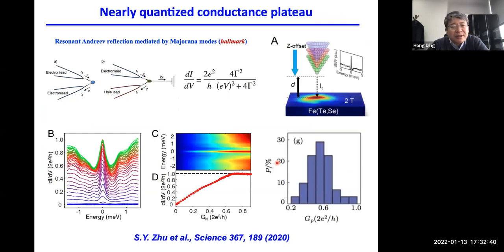We also did this to check whether or not we have the quantized conductance, as first proposed by Patrick Lee and colleagues. They proposed that this is actually a resonant Andreev reflection. If you have a Majorana mode, the dI/dV, the conductance, will reach 2e squared over h, the quantized conductance.